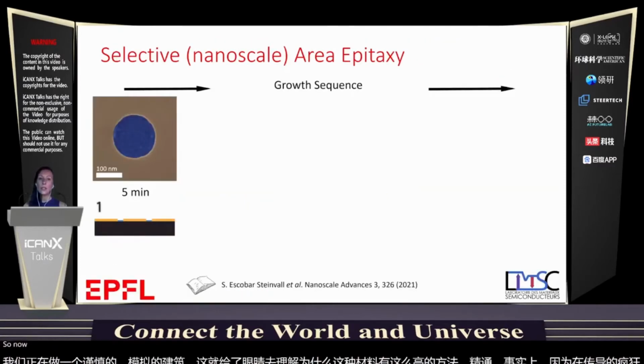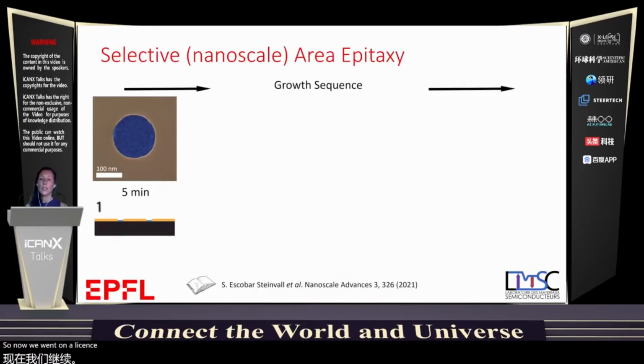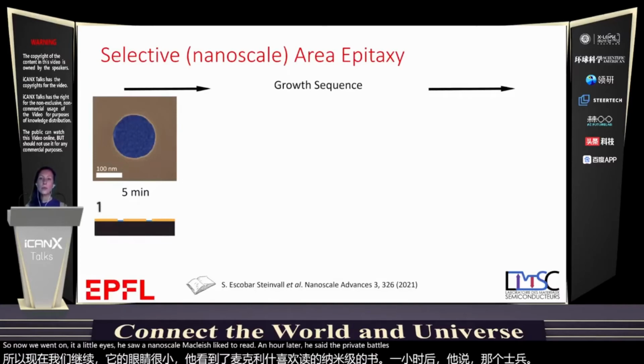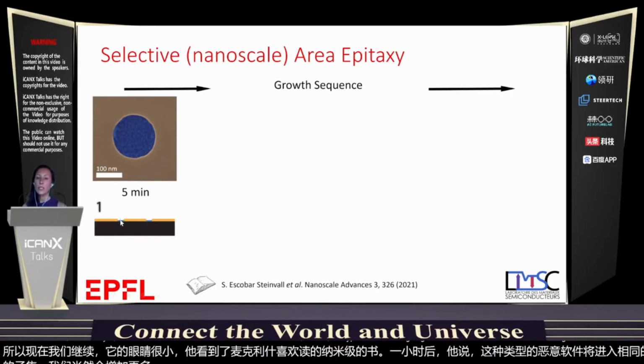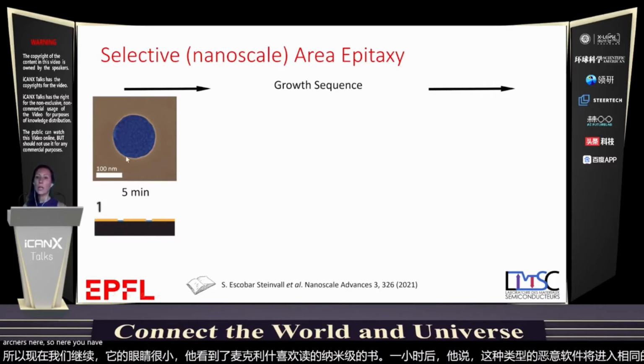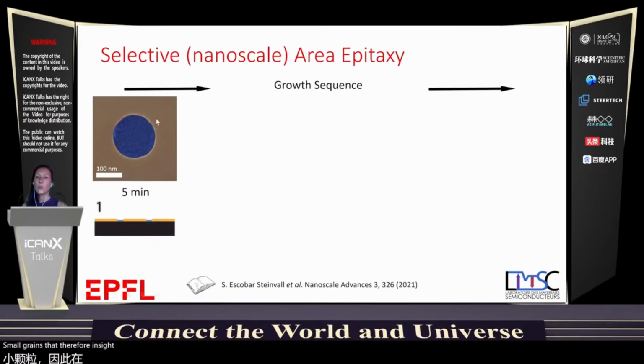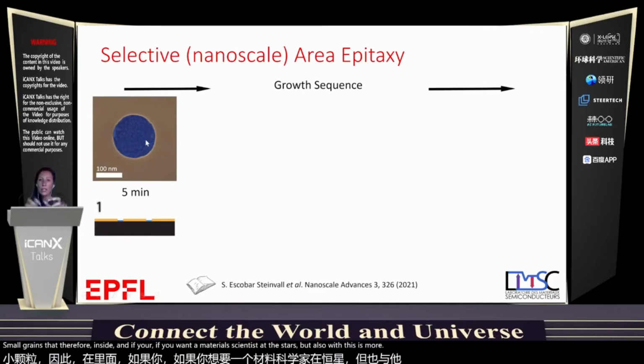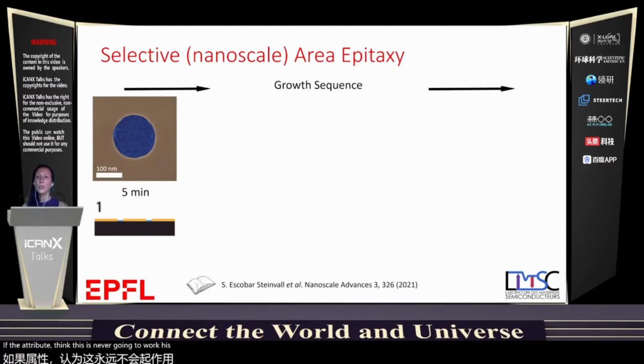So now we went on and utilized this nanoscale nucleation to go, instead of nanowires, to textured thin films. We started again with a substrate that has some pattern, and we started growing on these nanoscale patterns here. So here you have the growth after 5 minutes. You have these small grains that are formed inside. And if you are a material scientist and you start seeing growth with these multi-nuclei, you would think this is never going to work. This is going to give you a polycrystalline material. It's not going to work at all.